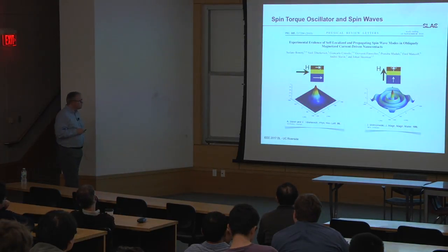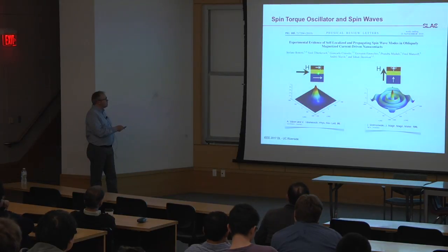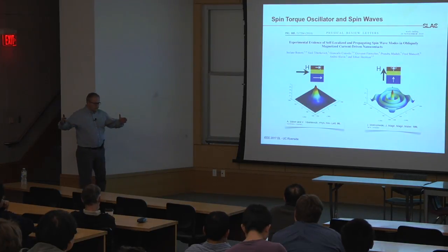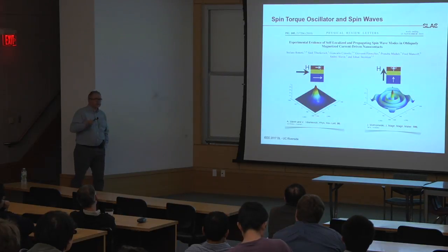In principle, one distinguishes between two different cases. The blue layer here produces the spin polarized current, which you separate from a ferromagnet with a small non-magnetic layer, and then inject into the second ferromagnetic layer. You induce dynamics here because the magnetizations are not 100% aligned, they're a little bit misaligned, and by doing so you start to wiggle them a little bit, and these wiggling motions can excite collective motions of the whole thing, which can have different shapes.